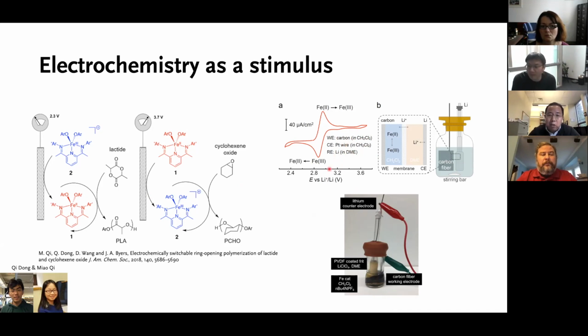Another thing I wanted to point out is the reference, in order to accurately calibrate the potential at which iron is reduced. Qi cleverly used lithium iron phosphate, which is a known cathode material for lithium ion batteries. A unique property of lithium iron phosphate is that it features very stable electrochemical potentials over a wide range of lithium composition. That's very reliable, and it can then be converted to what's very commonly used in organic chemistry, such as ferrocene/ferrocenium.